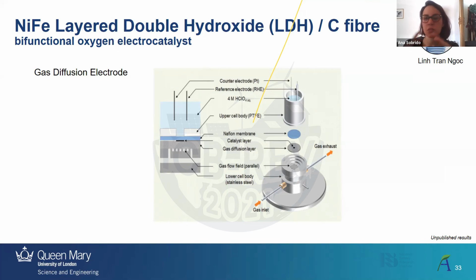What happens with that is that you need to prepare an ink and then drop it onto your rotating disc electrode. We don't want to do that because we want to test the freestanding mat as it is. So we were really lucky to find this group, which has a system where you put your freestanding mat here, and the gas flows underneath and is in contact with the catalyst layer. Then we have an anion membrane, and then an electrolyte. So it's quite close to the actual conditions in a water electrolyzer, for example.